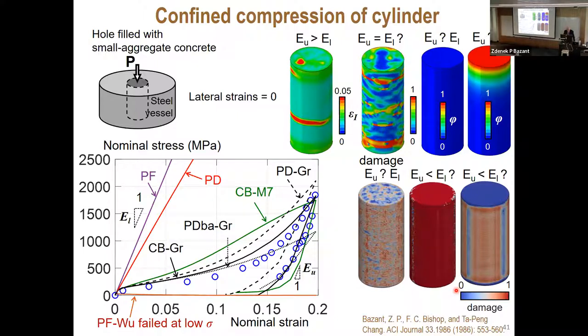Now, confined compression cylinder, perfectly confined. That's not a fracture test, but it's very important for penetration of missiles into concrete or rock walls, because at the moment of penetration, material is under enormous pressure, many times higher than unilateral compression stress, and creates a zone which is basically plastic, it dissipates lots of energy, and only then fracturing starts. So we studied that extensively at Northwestern, and these are tests we did here with Bishop in the 1980s.